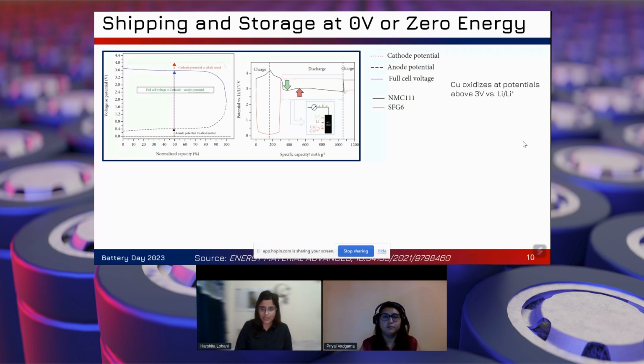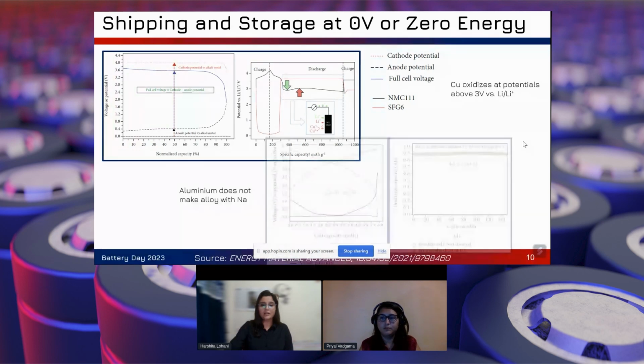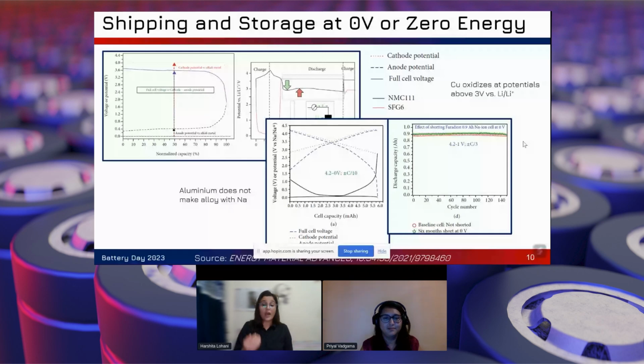Sodium ion cells have the potential to be discharged to 0 volt or even less than that. Faradion, one of the pioneer companies in this field, tested sodium ion cells at 0 volt storage for 6 months, and then compared their performance with short-circuited cells and the normal cells which were not shorted, and they found very little or minimal difference between the performance of the two cells. They confirmed that sodium ion cells can be shipped and stored at 0 volt or 0% state of charge, and this makes this battery safer, especially when we transport or store them in an area.